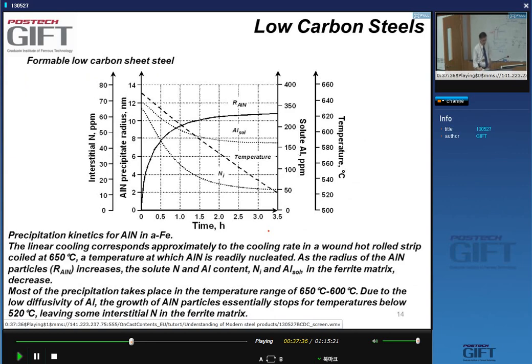Now, why is it that in the ferrite, when you cool down and the solubility of aluminum nitride is so low, below a certain temperature you don't get these particles growing anymore? Why doesn't the aluminum nitride grow? Well, it's actually very simple. So imagine I have already an aluminum nitride particle in a piece of steel, so it's ferrite. Solubility of aluminum nitride is almost nothing. You cannot dissolve it.